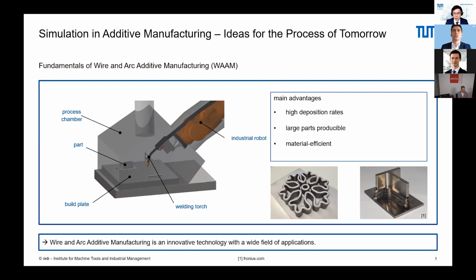The key advantages of this technology compared to, for example, powder bed fusion is its high deposition rates of up to several kilograms per hour, depending on the material. And in addition, we are also able to produce very large parts, since in theory, we're able to utilize the whole range of the industrial robot. Furthermore, we have a very robust, clean, and material efficient process, since all of the problems related to metal powder become superfluous. In WAM, we use wire primarily, so we do not have to worry about powder contaminations, powder aging, and other powder-related safety concerns.